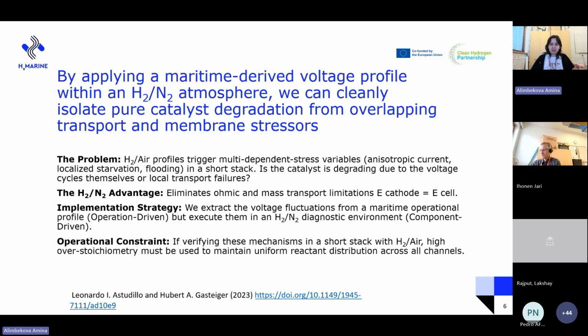But of course, to validate this complete picture, we eventually have to cross-reference our findings with the real-world hydrogen-air conditions. As a reference here, the Astudillo and Gasteiger paper pointed out that when moving the AST protocols from hydrogen-nitrogen to hydrogen-air atmospheres, it requires adjustments, particularly modifying the cell voltages to account for ohmic resistances, which would be different depending on the state of the system.